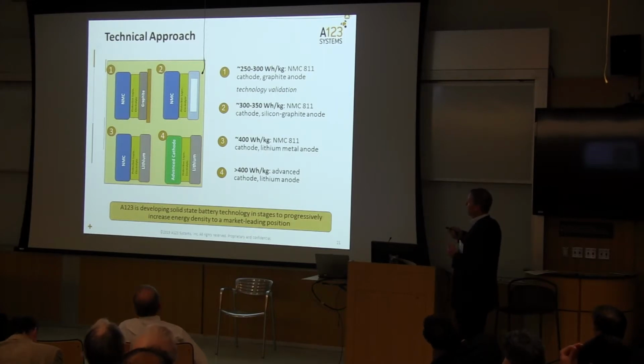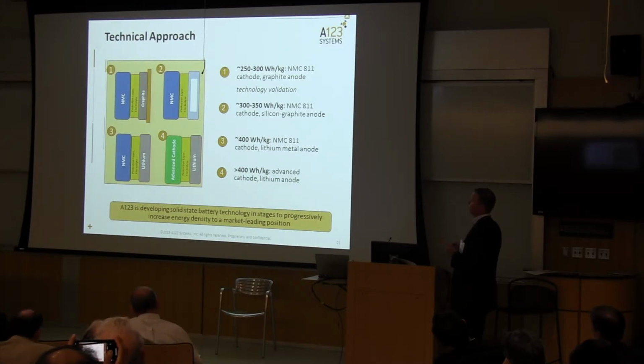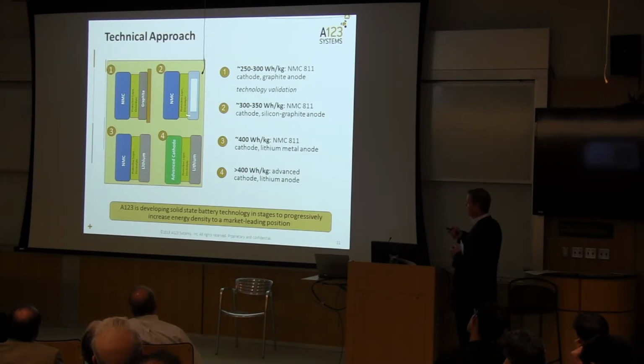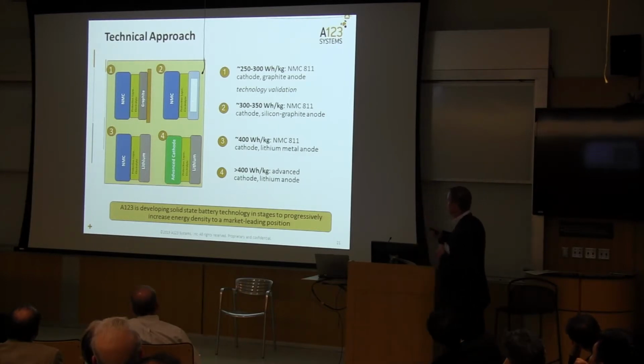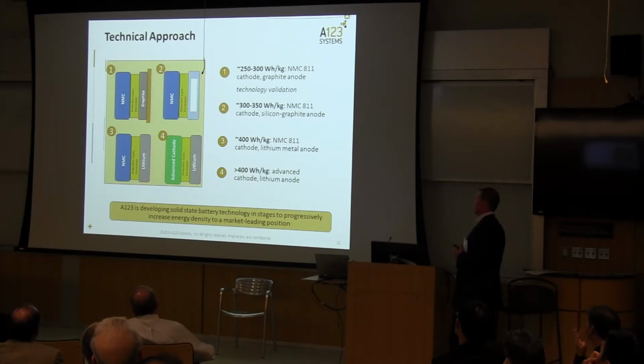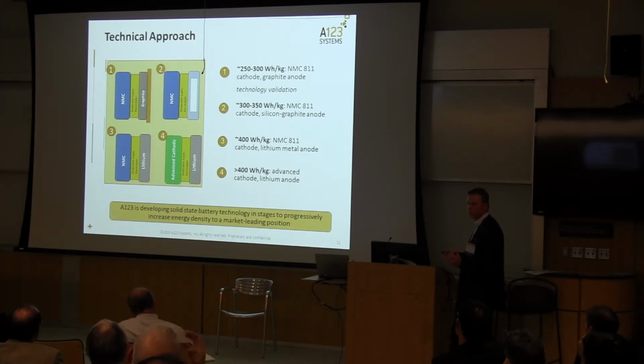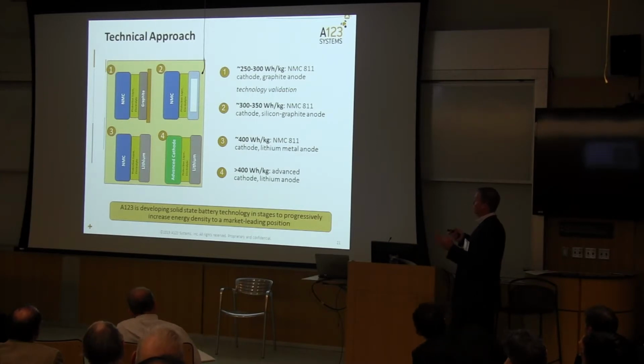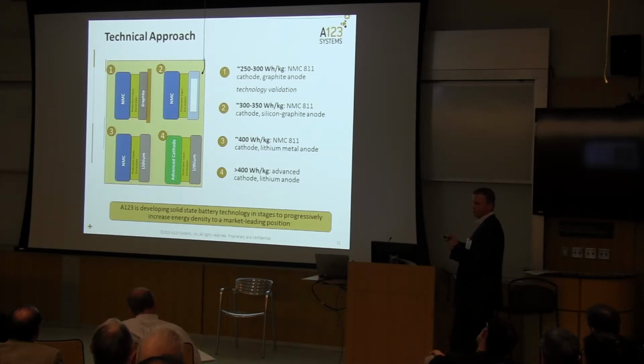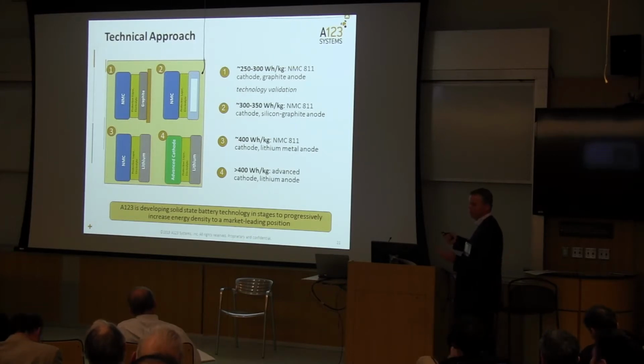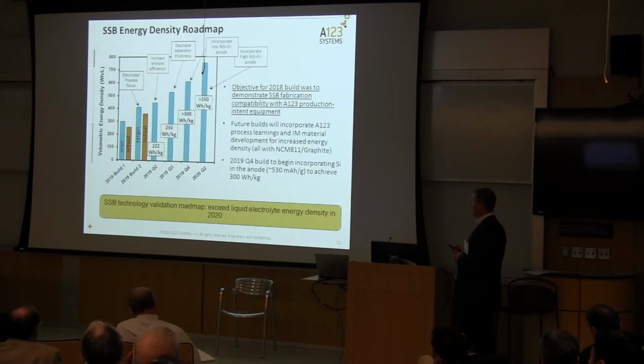How we're getting there is we're actually taking a staged approach. We're doing a proof of concept with just 811 and graphite and overcoming some of the issues inherent with the interfacial resistances and taking this to manufacturing. So this is the proof of concept, and right now we're between 1 and 2. And then this is actually silicon. It doesn't look like it came out very good, but this is incorporating silicon in the anode. The reason why we're staying away from lithium, at least right now, is exactly what was discussed earlier: you have this additional issue in terms of dendrite formation. So what we're trying to do is get to between 300 and 350 watt hours per kilogram with traditional materials in the solid state, so that we can demonstrate that it is viable for the automotive market without having to solve everything at once and jumping right to a lithium metal anode. And we think it's paying off.